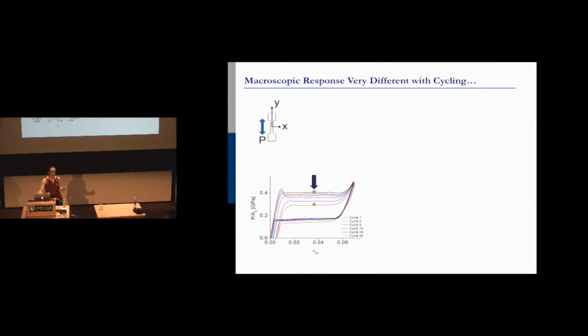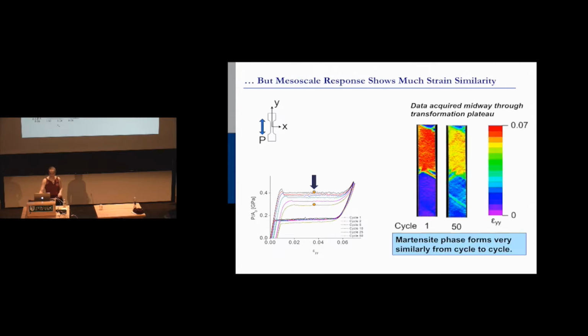And we took images at the midpoint of transformation for cycles 1 through 50. And when you look at those, what we saw was that there seemed to be a lot of similarity straight off the bat. We just started noticing this, and some things flip around. This flipped mid-cycle, but you've got a lot of similarity here. It's just something visually that we saw. And then we quantified it. So the martensite we saw was forming very similarly from cycle to cycle.